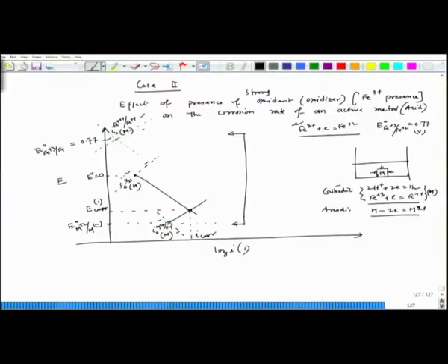So now it would come like this, and once it reaches this particular point, immediately it is seeing that there is another cathodic reaction, which is the hydrogen evolution reaction. So as per our concept in the previous example, we have to add up the total cathodic current densities.